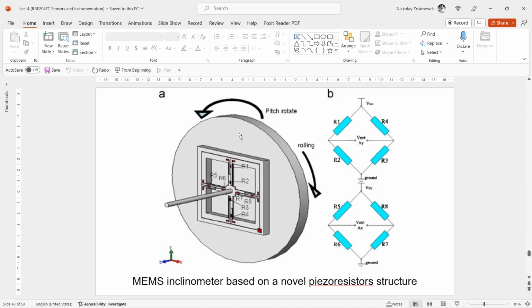One micro machine inclinometer was proposed based on silicon piezoresistive sensor. The sensor consists of a micro mass suspended on a thin beam. As you can see, this beam in the middle, and gravity forces the mass to move towards the Earth's center of gravity. And the resulting bending of the beam is measured in two directions by properly positioned integrated piezoresistors. The average sensitivity of this device is about 4.1 millivolts per degree, over a range of plus minus 70 degrees of inclination.